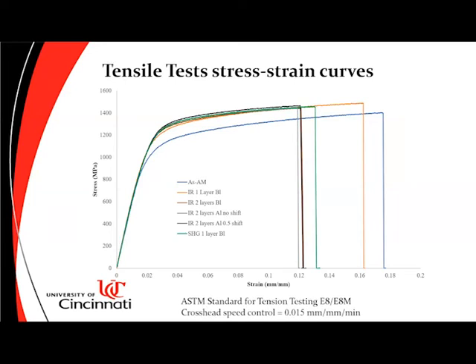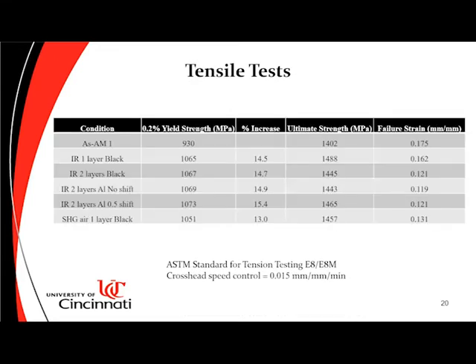Moving on to the results of the tensile testing, you can see the increase in strength of the laser peened samples is very obvious here, but this comes at the expense of a drop in the ductility. This table summarizes the result of the tensile test showing LSP increases the yield strength of this alloy by around 15%. But that comes at a cost of reduction in the ductility. There's not much difference between the conditions.